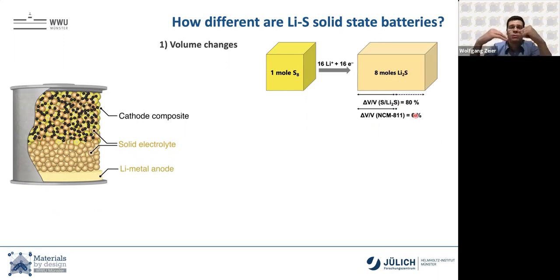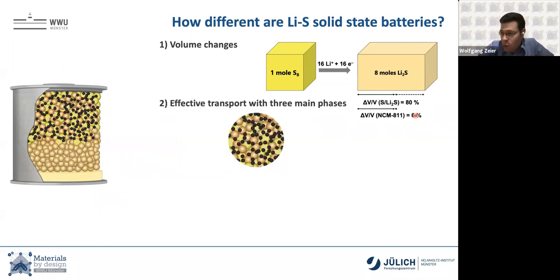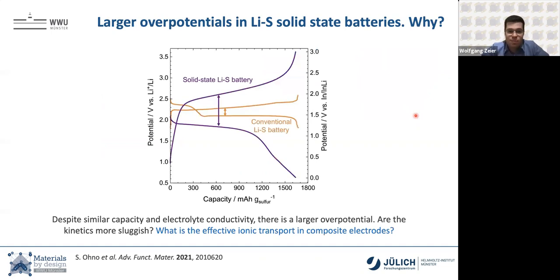And the 6% are already a problem if your active material is breathing right next to a grain of an ionic conductor. An 80% volume increase is a problem. But even more so is that now we need transport in 3 main phases. It's no longer just 2, but now it's 3. It's carbon that we need because sulfur is an electronic insulator. It's sulfur, our active material, and it's our solid electrolyte. And why is this a problem?